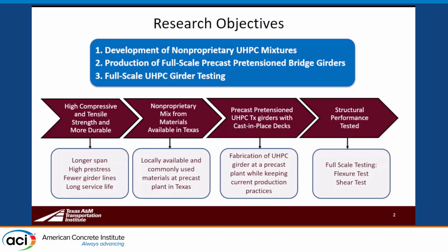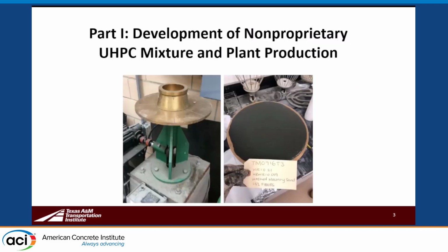And so the first thing was that they wanted to look into developing a non-proprietary UHPC mixture to reduce the cost of using UHPC for large members, and also to specifically tailor the mix towards high early strength concrete needed for pretension bridge girders. So as part of that development of the mixture, we also needed to implement it into a precast production process, and so we moved it from the laboratory to the precast plant, and then finally cast girders and tested them to look at the structural performance. So part one of this talk will focus on the production and development of the non-proprietary UHPC mixtures.